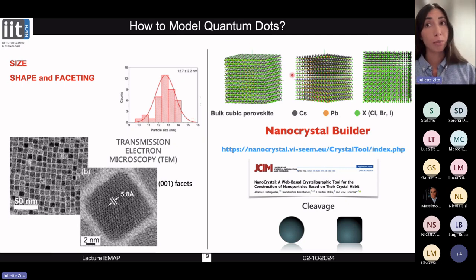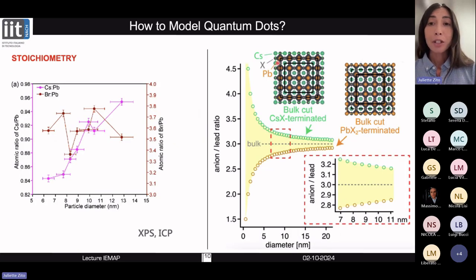So now from the computational point of view, once we collect this information, we start from the bulk structure of the perovskite, in this case, the cubic lattice. And we will use this online tool called Nanocrystal Builder to cleave the bulk with the correct size, the correct faceting, and the correct shape. However, when we cut a cubic bulk, we can end up either with a model that has this cesium halide termination, and in this case, the anion to lead ratio is higher than the one in the bulk, so higher than 3, or you can end up with a lead halide termination, and in this case, you have a lower anion to lead ratio with respect to the bulk.